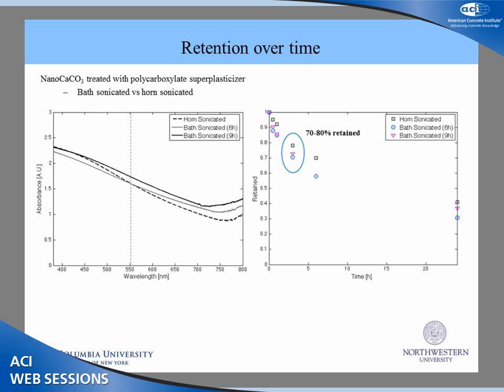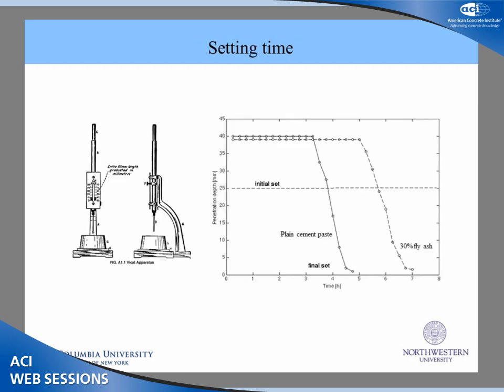So instead of subjecting these suspensions to centrifugation, we just let it sit and then monitor the absorbance over 24 hours. And we compare this for both bath-sonicated and horn-sonicated suspensions. This is the initial absorbance spectra, very similar, and then this is the retention over 24 hours. And you can see that within 3 hours, 70 to 80% are still retained. So this means 70 to 80% of the particles are still suspended, and we can cast these samples well within this 3-hour time frame. So from there, we use those suspensions to prepare paste samples for mechanical testing.